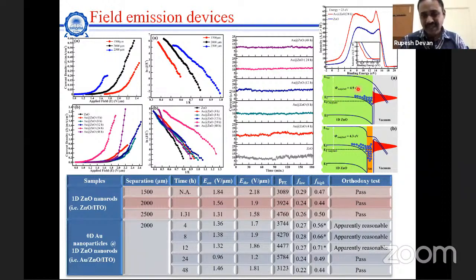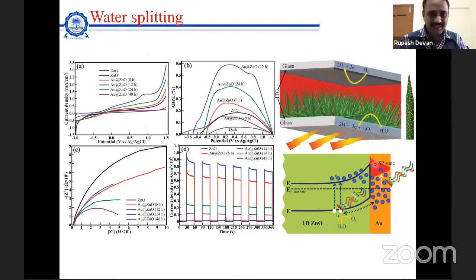The electrons in zinc oxide, which were moving to the conduction band, were providing the emission. Here, because of this gold, they were accumulated together, and this was supported by zinc. So a larger number of electrons were provided by zinc and gold together. That's why we could get better results out of it. Then we checked the water splitting. You can see as soon as you increase the gold concentration, the current density is increasing.